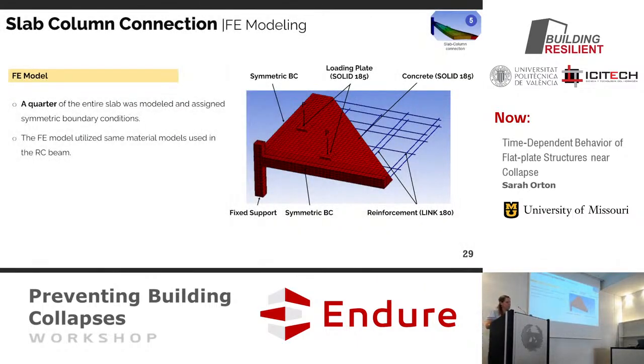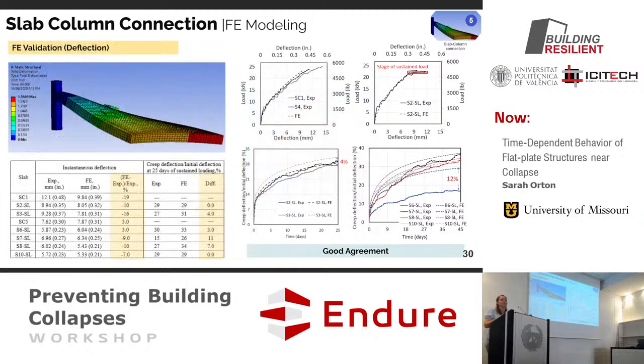Did modeling of it, of course, using the ANSYS model, used the same configuration of the model that we did in the beam test. We tested it out in the beam test. We applied the same theories and ideas to our slab test, and we're able to get really good results. We didn't have to modify the model, do lots of changes to match the data. Once we got it set with the beam tests, it worked out really well.